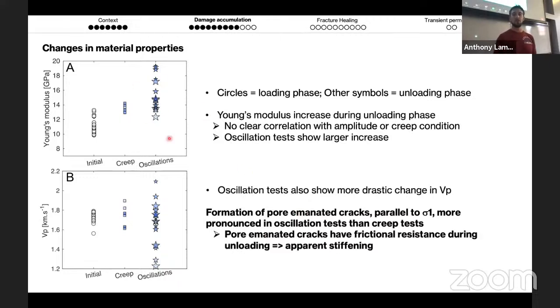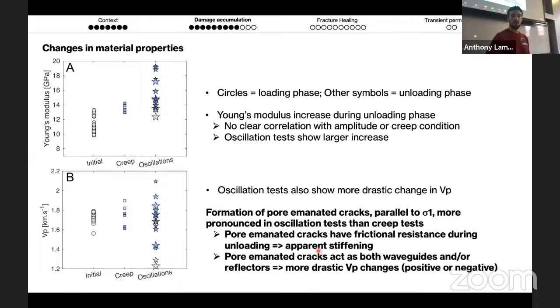And the result for the Young's modulus is counterintuitive, because what I think happens is that these pore-emanated cracks will have some frictional resistance during unloading, and therefore give an apparent stiffening of the rock. And that goes opposite of what people have shown in the literature. And also these pore-emanated cracks might be able to, depending on their size, act either as a waveguide for my P waves or as reflectors, and therefore give me an apparent change in velocity that is either increased or decreased, depending on their size, their orientation, and everything.